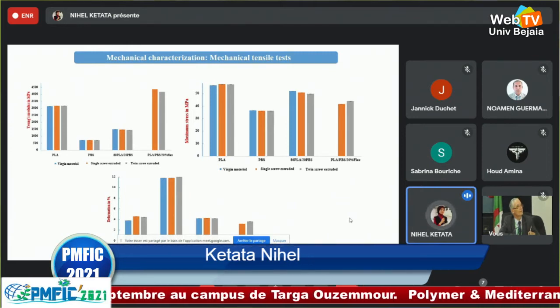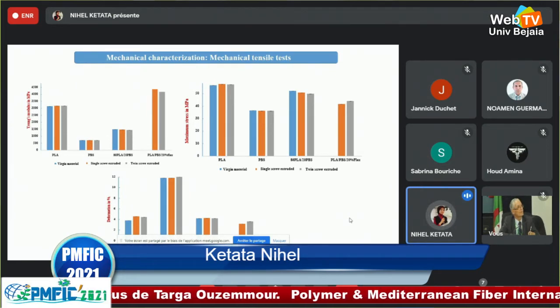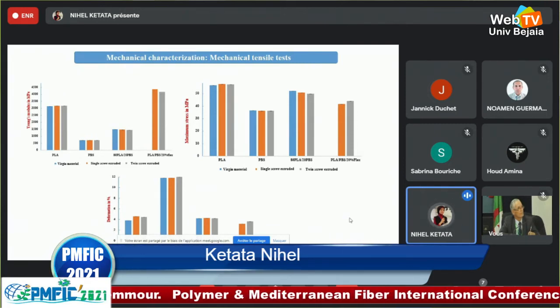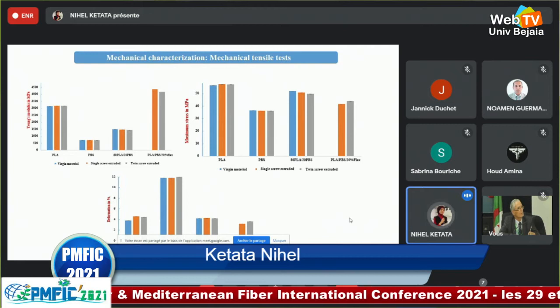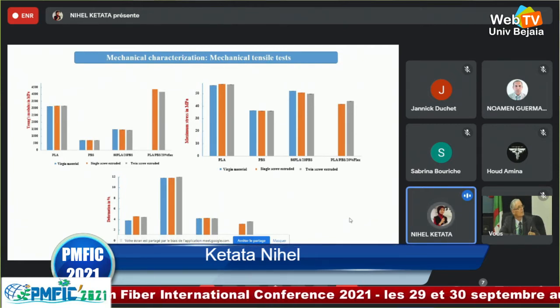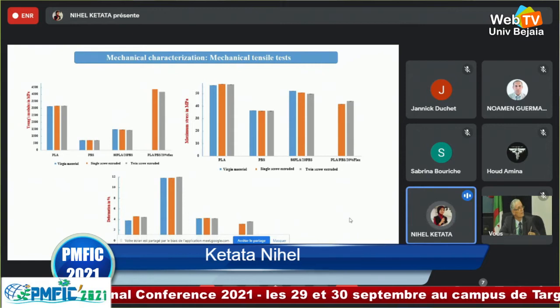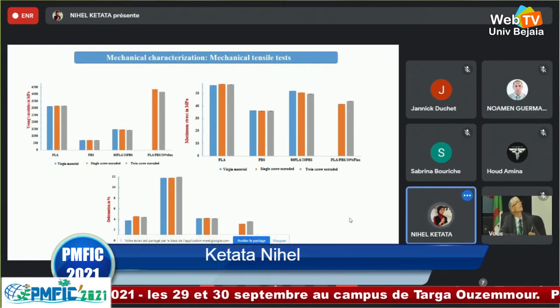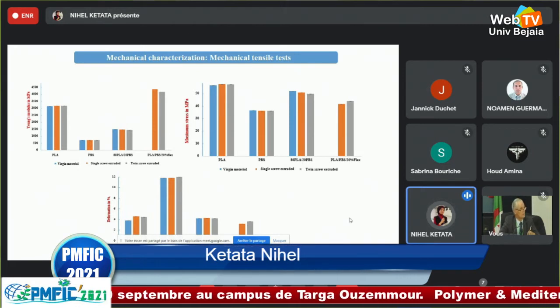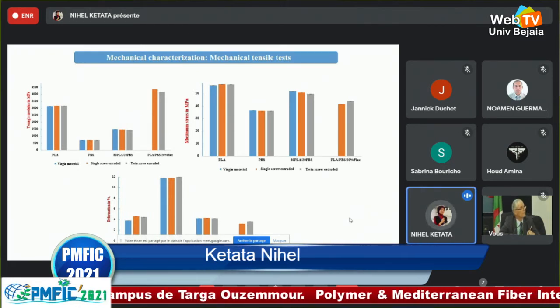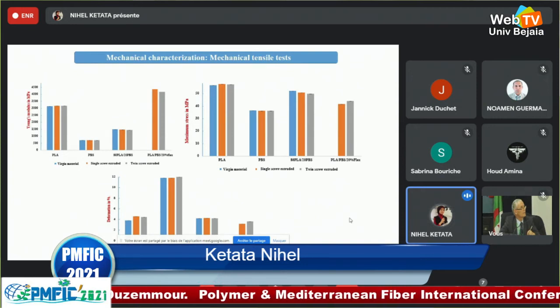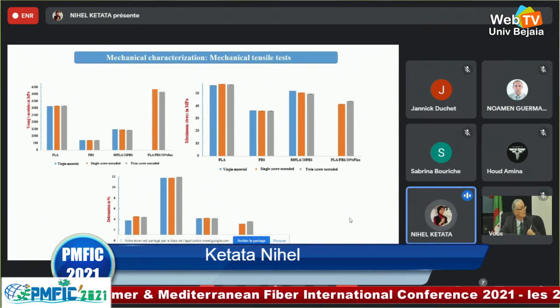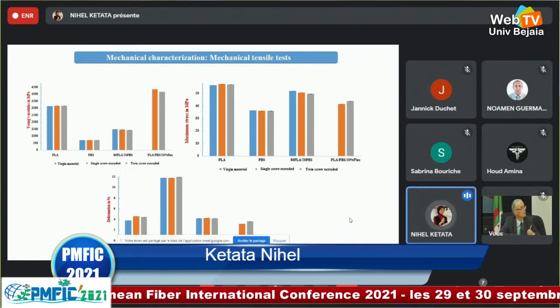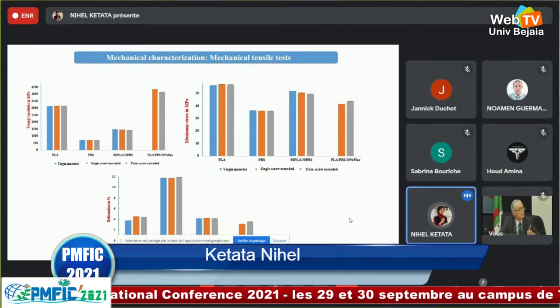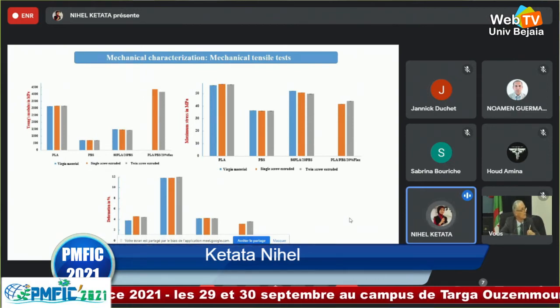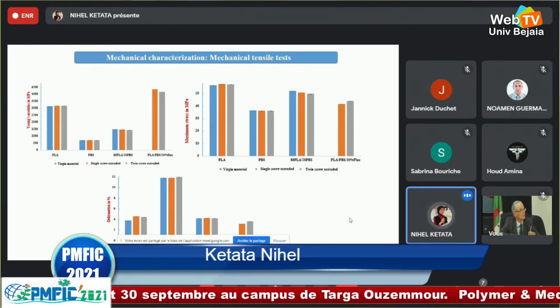Here we measured the Young's modulus and the maximum stress of PLA and the deformation at break. As we can see from the figure, the Young's modulus of PLA and PBS and their mixture are not significantly changed during single or twin screw extrusion. On the other hand, the Young's modulus of the flax fiber reinforced composites is significantly higher than PLA, PBS only, or their mixture. The Young's modulus of the single-screw extruded flax fiber reinforced composite is slightly higher than the twin-screw extruded composite.